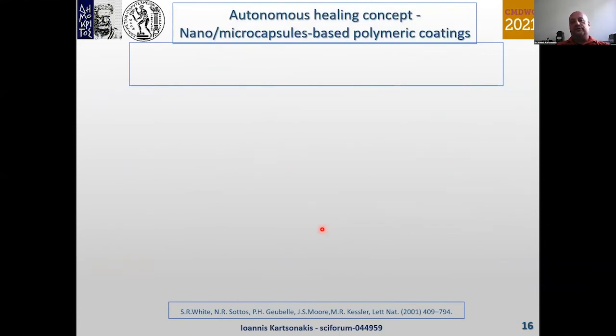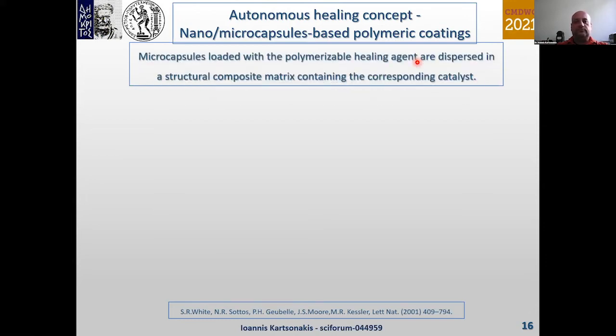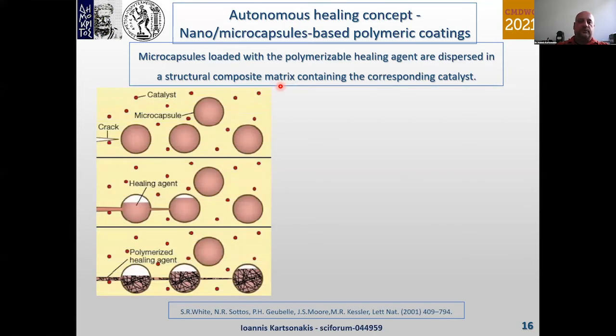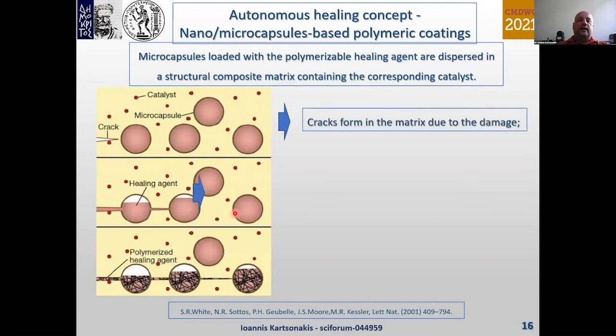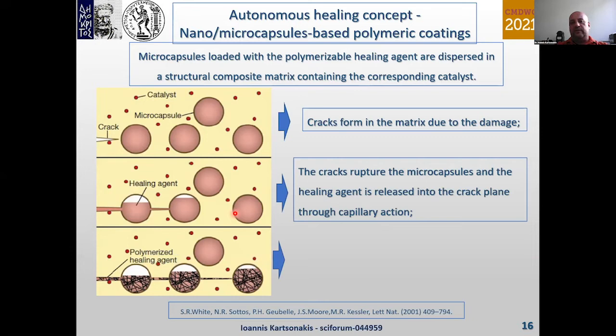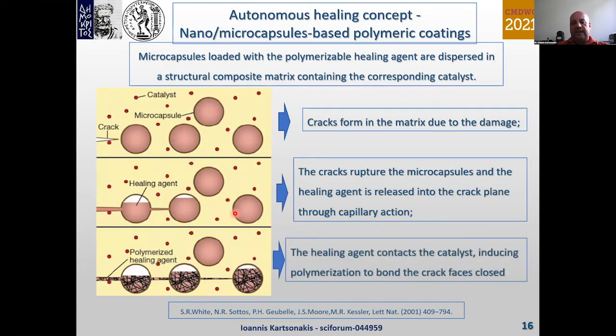So the category of autonomous self-healing coatings including nano and microcapsules incorporated into polymeric coatings. These microcapsules can be loaded, as we said before, with healing agents that can be polymerized. These loaded microcapsules can be dispersed in a composite matrix that also contains a corresponding catalyst. We can see from the work of White in 2001 how these microcapsules work. After the crack formation in the matrix, the microcapsules are ruptured, the healing agent is released from the microcapsules and reacts with the catalyst, and the outcome is a polymerization that bonds the crack faces closed.